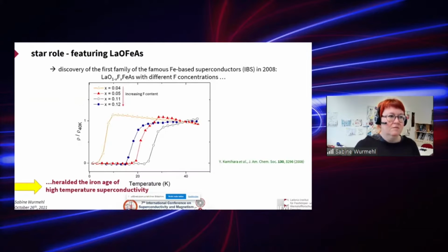The pnictides with rare earth and oxygen iron arsenide were the first ones reported in 2008, and you can establish superconductivity upon the suppression of the spin density wave with fluorine doping, finally establishing superconductivity, as you can see here in this plot.